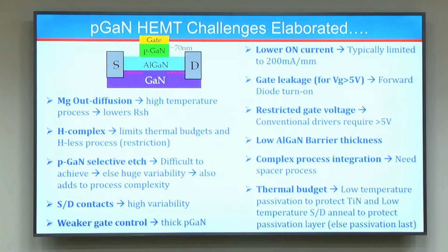And that's very difficult to avoid in this case, which means you are talking about developing a process which is a low temperature process relatively compared to a D mode kind of stack. Hydrogen complex, if you have hydrogen complex formed in the pGaN, then the magnesium, the active p dopants present in the pGaN layer, will become inactive, and therefore the depletion which was present, or the p-type doping concentration which was present, will basically vanish. So you have to avoid processes which are rich in hydrogen, or if you have done such processes, you have to do a different kind of anneals to get rid of those hydrogen complexes.